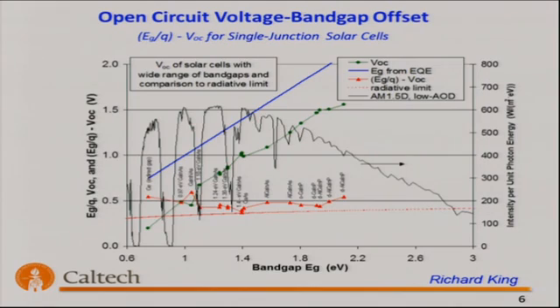This is a plot here from my friend Richard King at Spectral Lab, in which he made a systematic study. This is a plot of the solar spectrum, and this is the band gap of semiconductors, and then these points here are the open circuit voltages, versus band gap, on a unity slope plot. And you can see there's a systematic offset between the band gap and the open circuit voltage for a variety of high quality epitaxial single junction solar cells. Here, germanium, gallium indium arsenide, higher band gap gallium indium arsenide, aluminum gallium indium arsenide, gallium indium phosphide, aluminum gallium indium phosphide. If you do that subtraction, you can see there's systematically an offset of about 400 to 500 millivolts that's coming from those terms.